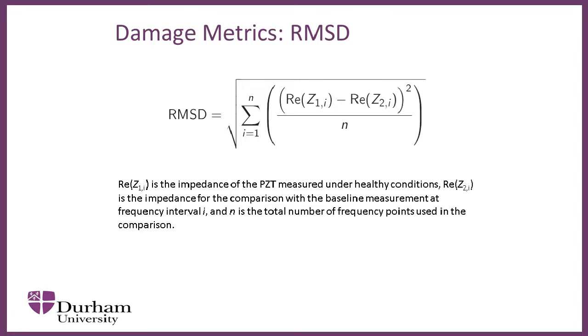So the baseline impedance measurement of the 5 transducers was made with an undamaged pipe, with a frequency range of 10 kHz to 20 kHz in steps of 5 kHz. Subsequently, damage was made to the pipe, and impedance measurements within the same frequency range and frequency steps were made for all 5 transducers. The damage conditions investigated are listed here, where the distance x and the angle theta of each of the holes drilled are referred to in the coordinate system shown in the previous slides.